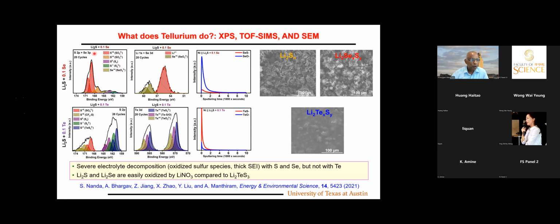You see here, more oxidized species here, more oxidized species here, less sulfide or selenide kind of species in the XPS. The same thing can also be seen in the case of ToF-SIMS. You have more oxidized blue here, less reduced species. So there is a big oxidation going on to form oxidized species. If you add tellurium, that kind of oxidized species is reduced. You have more sulfide and telluride kind of species. That is shown both by XPS as well as by time-of-flight secondary ion mass spectrometry.